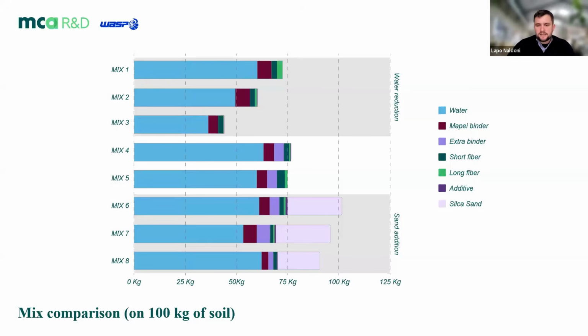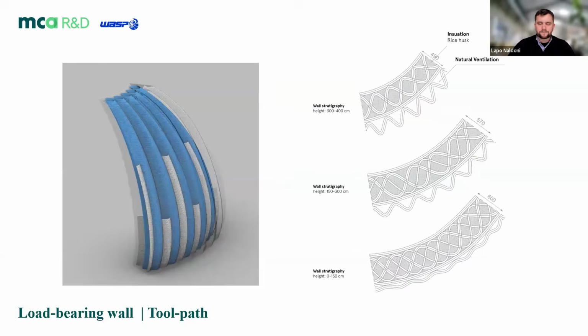So we decided to change the mix and started adding silica sand in order to reduce the shrinkage but have a more fluid paste during the printing. So with this printable paste, we started working with Milan Engineering, our consultant for the engineering part. And we decided to use a structural part, only the blue part, and the white parts that you can see on the left are just for the insulation and the ventilation of the wall. On the right, you can see how we change from the bottom to the top the amount of material inside the wall in order to reduce the weight of the wall. I mean, the material was earth, so we needed to find a strategy in order to reduce the stress on the material.